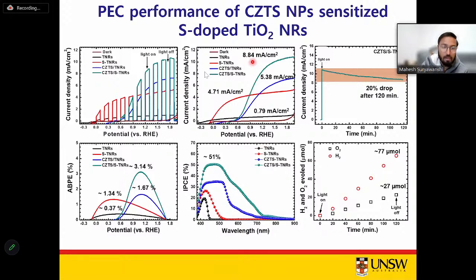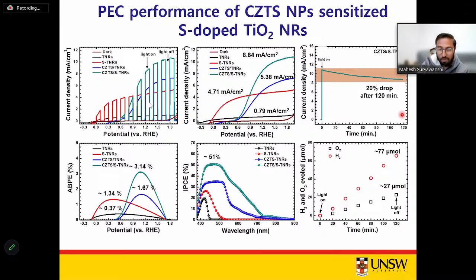However, the problem is when you test the stability of this whole photoelectrode system in water, you can see there is about a 20% drop in the initial current density after 2 hours. So you can imagine if we keep these photoelectrodes in a water system to produce hydrogen under sunlight, after 2 hours the photocurrent density is reduced by almost 20%, right? That means if you keep performing this water splitting reaction, let's say for 10 hours, the current density will drastically drop to almost zero. And then no more water splitting reaction will happen on the photoelectrode surface. That's one drawback of these chalcogenide compounds.